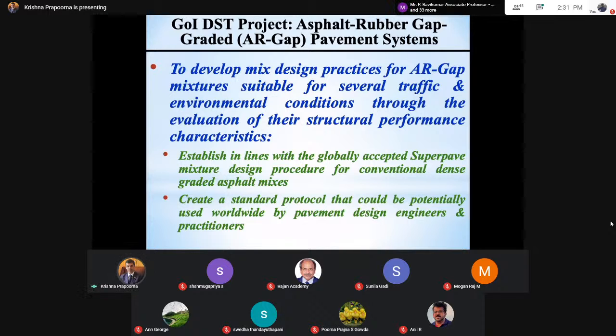So we wanted to do it from scratch, and to the best knowledge of our team, we were the first people in the world to use Superpave mixture design for asphalt rubber. In fact, even Arizona and California don't use Superpave yet for asphalt rubber as a specification. They still use Marshall mix design, which you are familiar with. So we fully went into the Superpave design, and that gave us a lot of confidence that this product will last for this many years. We checked with our lab facilities and experiments, and we went to the field and implemented it also. We also wanted to create a standard protocol, which is now pending with the DST.